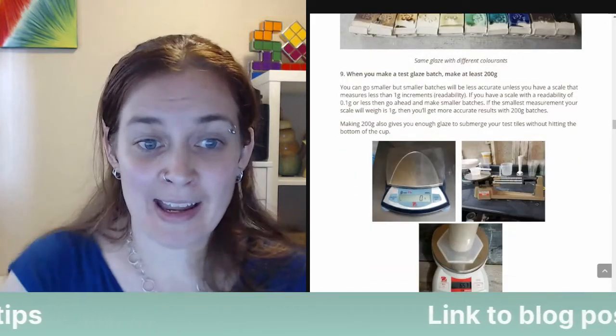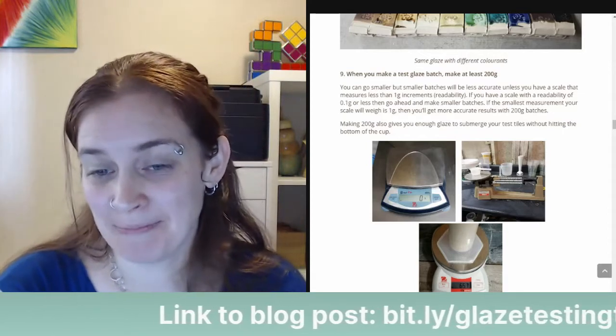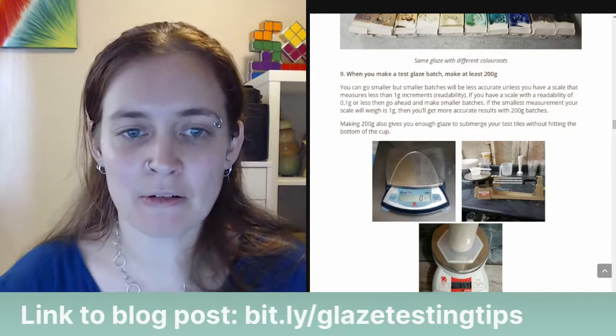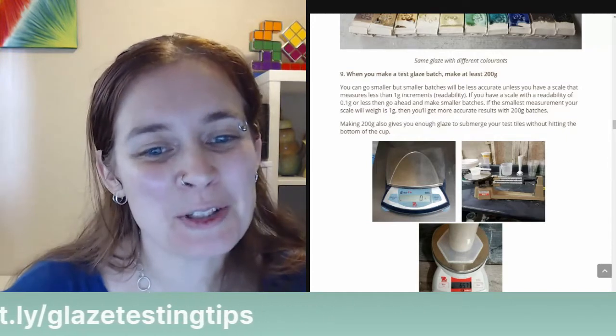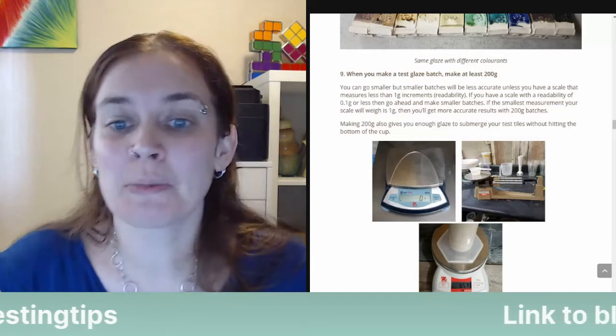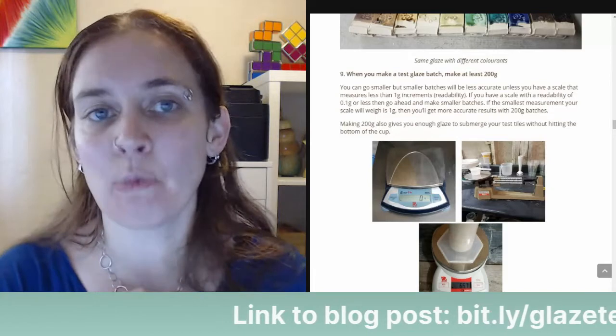Tip number 9, when you make a test glaze batch, make at least 200 grams. Now people might argue with me on this one, but this is what I do. You can go smaller, but smaller batches will be less accurate unless you have a scale that measures less than 1 gram